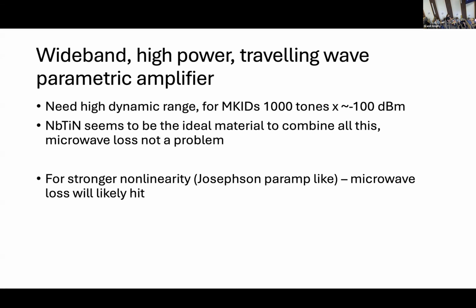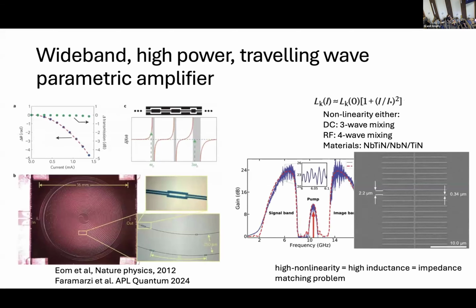It has two reasons. One is indeed that you don't want it to be crazy nonlinear, because then you can't handle all that power. The second has to do with this loss as well: if you went to higher inductance, then you get loss, of course, and this whole thing breaks down. Here you get a gain of about 20, well, more than 20 dB actually. But if you were further down in that loss plot that you just showed, this would obviously fail hopelessly, because you really need to amplify your signal before it gets lost in essence.